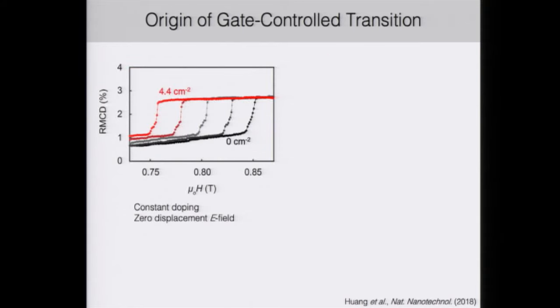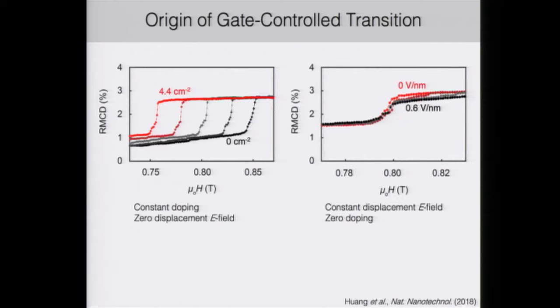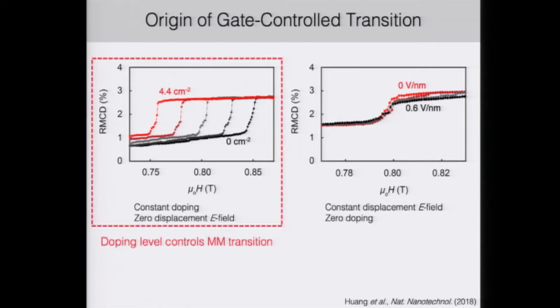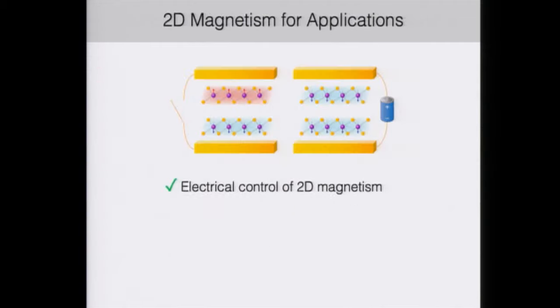And so here I'm showing what happens in zero displacement electric field at different constant doping levels. And you can see that we're able to change the magnetic field required to flip the spins in chromium iodide. When we have zero doping but different constant displacement electric fields, there's no change in the signal. And so we conclude that the doping level seems to be what is controlling this metamagnetic transition in chromium iodide, but a further microscopic picture still needs to be studied.